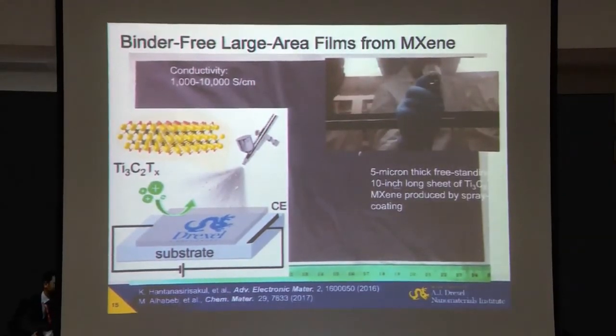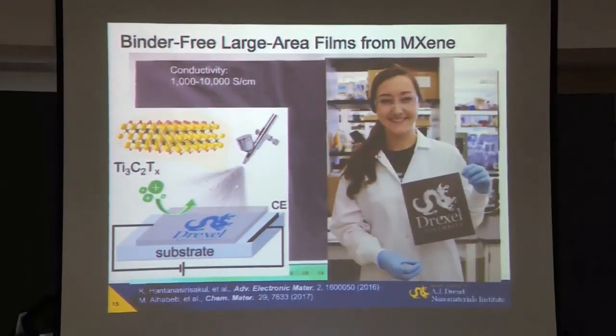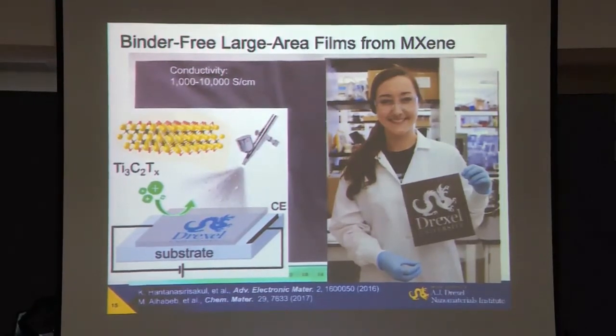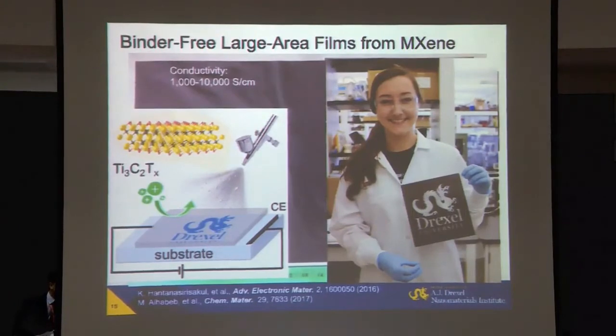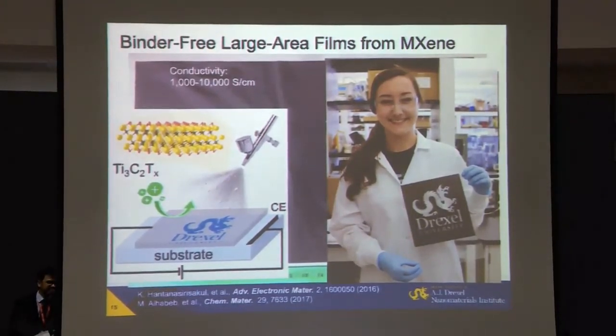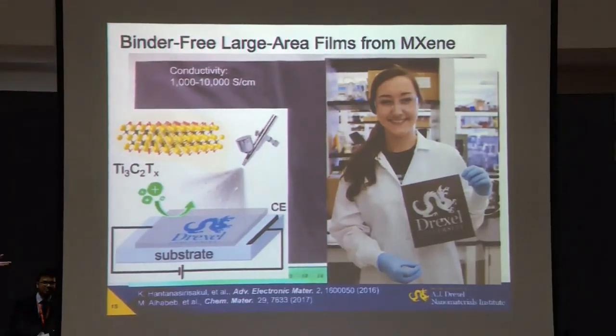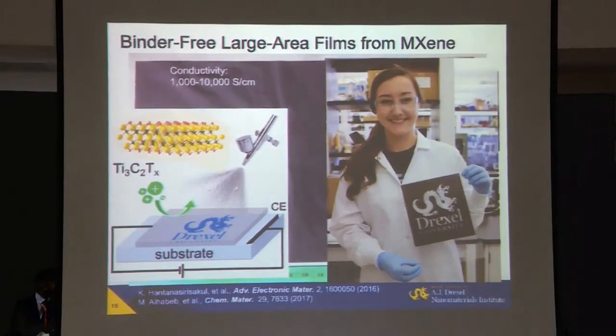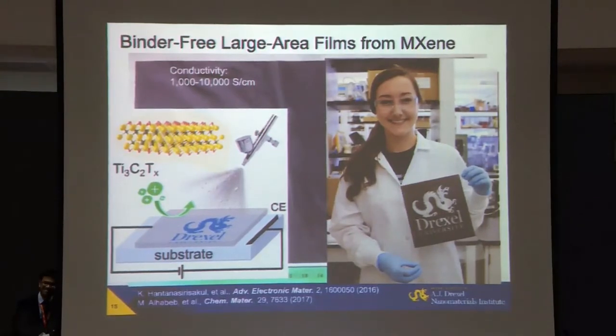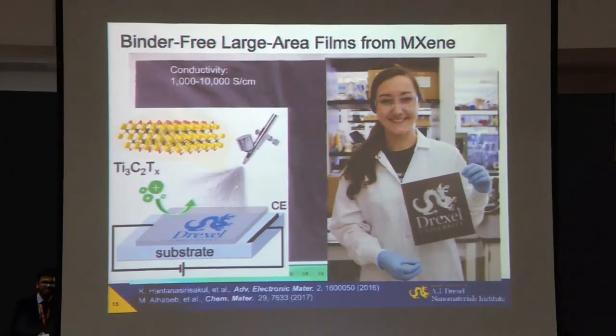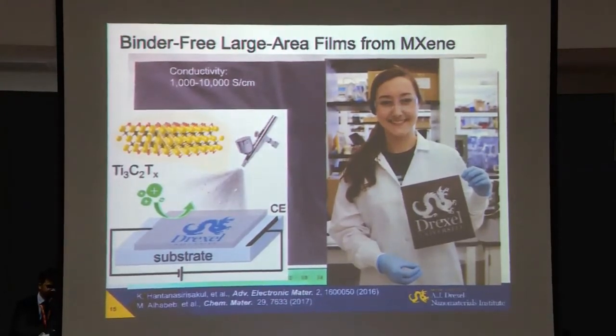Actually, the more graphene, reduced graphene oxide, you add, the lower is the conductivity. But we need it for energy storage purposes. And this is another student, Caitlin Maleski, holding a Drexel University logo, spray coated. So again, nanotechnology does not need to be nano quantity or $1 billion worth in expenses to build it here. You see, we use ceramic powder. We use cheap acid, for example HCl, and fluoride salt, like lithium fluoride, to etch here. And we use a $20 spray gun, I'm pretty sure in India it's probably even less expensive, the same you would basically use to paint walls or paint something else in your house, to produce nanomaterials with conductivity exceeding pretty much any two-dimensional material solution processed that is known here.